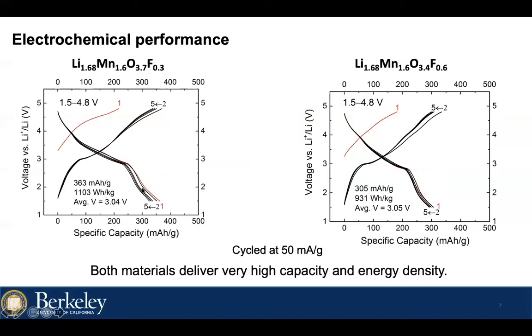And even if we cut the lower voltage limit at 2 volts, around here, it still can deliver a capacity higher than 300 milliampere hour per gram, and the energy is higher than 1000 watt hour per kilogram. And for the compound with a higher fluorination level, the initial capacity and energy density decrease, but still it's pretty high compared to typical cathode materials.